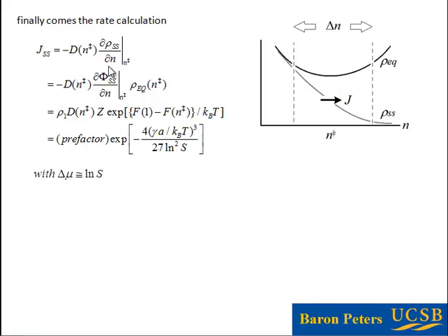We've got an intrinsically non-equilibrium steady state calculation that we're doing, but what we're going to do is write the steady state nucleation rate in terms of the equilibrium probability to be at the dividing surface. And the reason that pops out is because this is the thing that we want the gradient of, but this is the thing that we solved for. And of course, the equilibrium population, if I multiply this by this, I get back my rho steady state. Okay, so basically now just doing some math and using the definitions that we've already established on the previous pages, this thing turns into this formula.